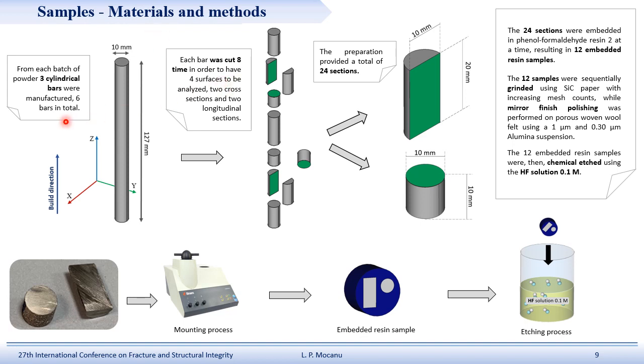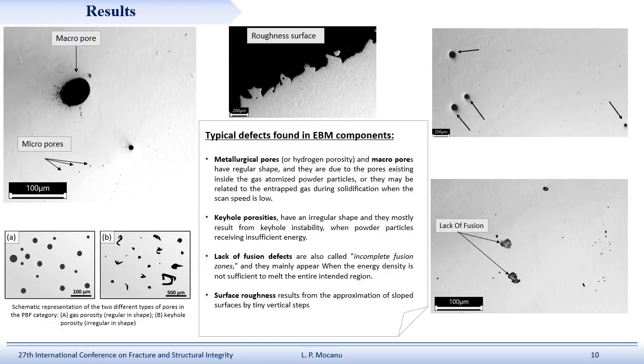Here we have the sample preparation. We started with these 6 bars and we sectioned them in order to evaluate the situation in the upper part of the component and in the lower part of the component, because we wanted also to see if there is any influence regarding the building plate. And then we simply performed metallographic preparation in order to obtain this embedded resin sample, and then through the etching process we investigated.